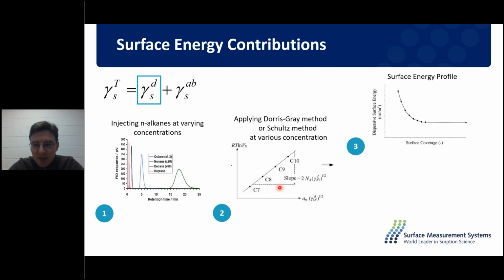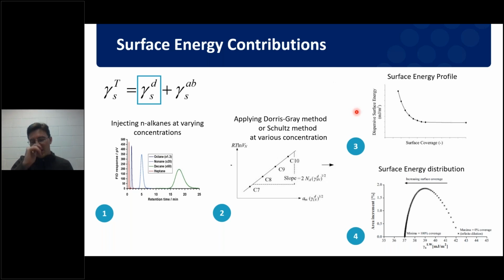So I did this exact thing at 20% surface coverage, 10% surface coverage, 5% surface coverage, and 0.5% surface coverage. I form this lovely surface energy profile. It is at the most dilute injections that I am analysing the highest energy sites, and it is at the most concentrated injections that I am analysing more of an average surface energy, and I'm filling those lowest energy sites. And from this profile, I can form a distribution.